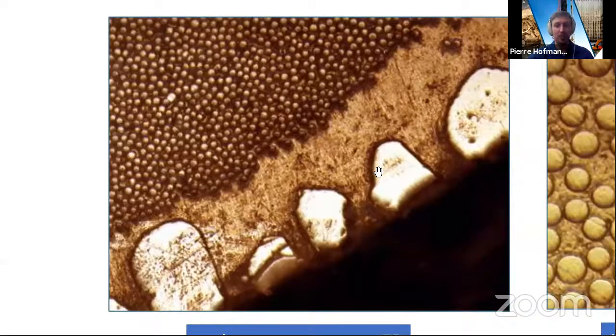You can appreciate the size compared to the individual glass fibers shown at the top left corner. You can see how tiny they are. They're only 15 to 20 micron in diameter. And this vast brown area here is actually resin. So we can see that the resin is really acting as a binder between the fibers on the outside and the glass on the surface.